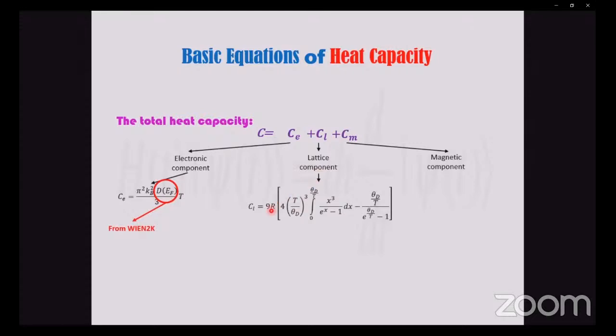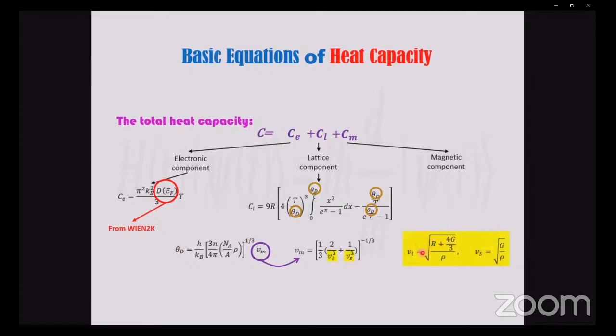The lattice component is given by this equation, which depends on the Debye temperature that we can obtain from this equation in terms of the mean velocity of wave. The mean velocity of wave we can get in terms of the longitudinal and transverse speed of wave, which in turn can be calculated from the bulk and the shear modulus obtained from the IRelast code implemented in WIEN2k. Finally, the magnetic component can be calculated from the mean field theory.